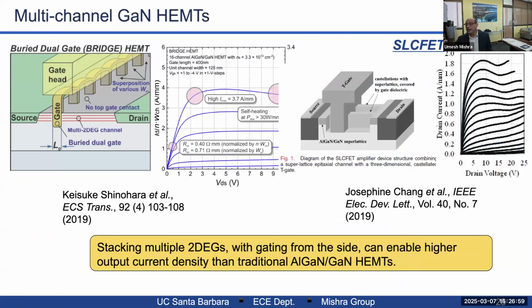There have been multi-channel gallium nitride HEMTs. You see, gallium polar gallium nitride HEMTs are good, but they have some issues with current. They don't have enough current and so on and so forth. More current is better, especially at millimeter waves. Because if you have low current and high voltage, and the only way to get power is to have high voltage, the load line is very shallow, i.e. the impedance is very high.